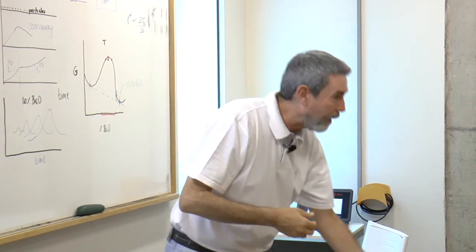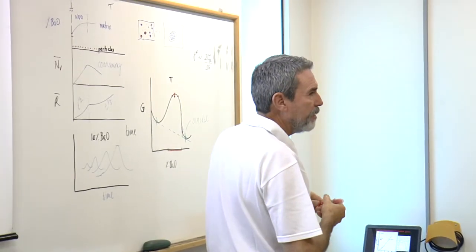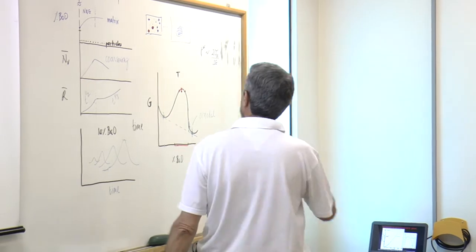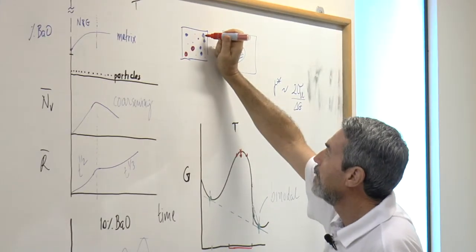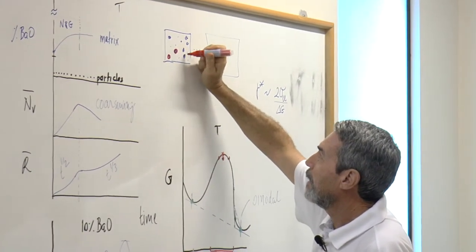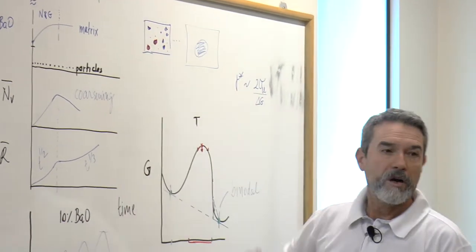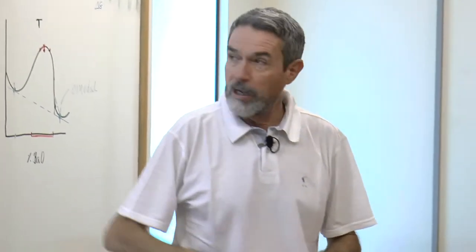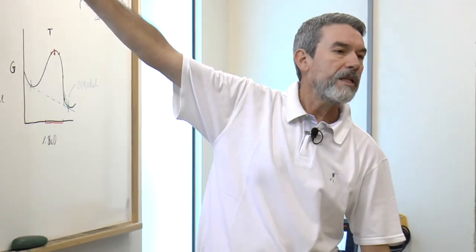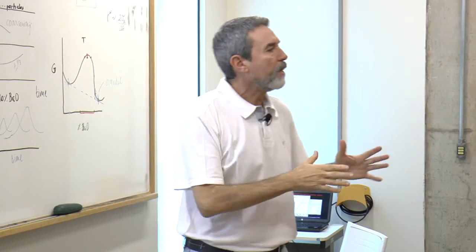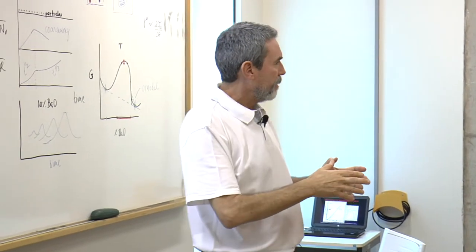Some people said, well, you form phase separation, then there are these interfaces, and they act as heterogeneous nucleation sites for crystal nucleation. But we are proving here that this is not the case. It's just a compositional effect.